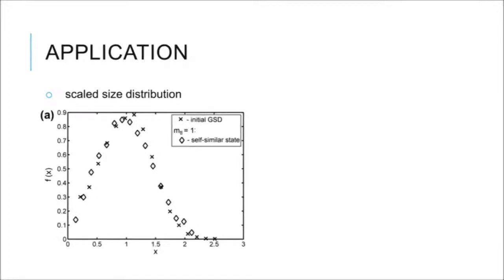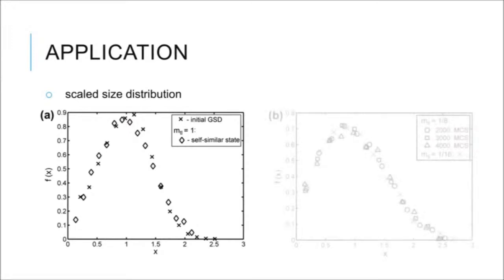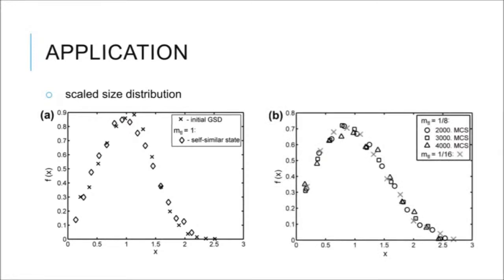Now, what happens if I reduce the triple junction mobility? You can see the result here—I've reduced it to 1/8 and 1/16. For such low mobilities, we still observe self-similarity, so we do have this linear growth kinetics. In addition, the size distributions show self-similarity, meaning the scaled size distribution does not depend on annealing time, but its shape is completely different compared to the one we saw on the left.